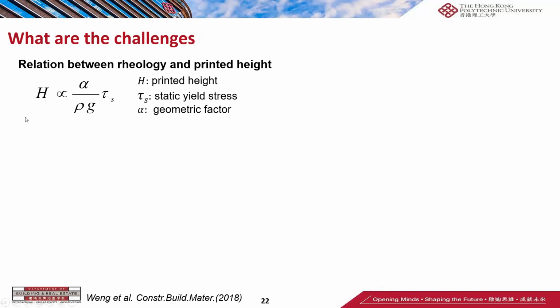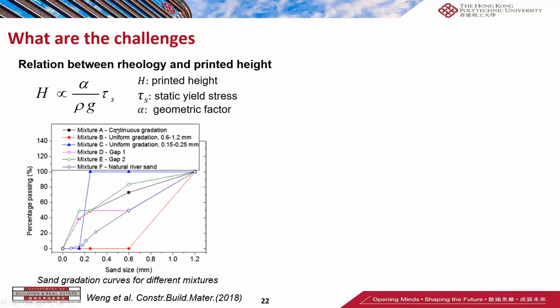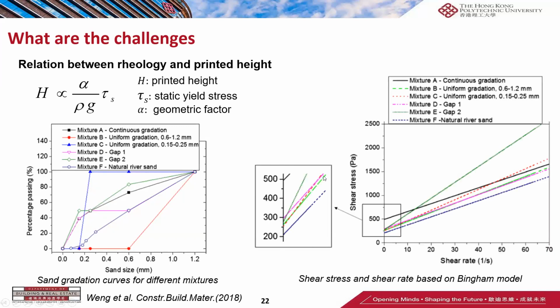So in this case, a model was built to correlate the relationship between the material property and the printed height of the materials. To achieve materials with different rheological performance, different gradation methods were adopted in the material mixing process. We are using the continuous gradation, the uniform gradation, and the gap gradation, and also the natural river sand for the material mixing. And then we measure the material rheological performance. Basically, you can find that they have different rheological performance with respect to the material yield stress.